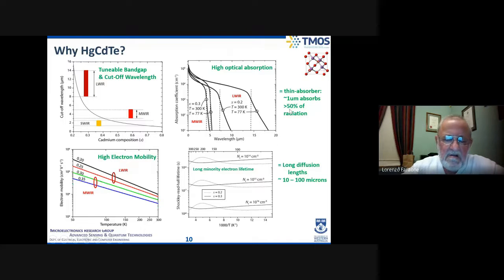So if I have a layer of mercury cadmium telluride that's maybe 4 or 5 microns thick, then I can basically absorb 100% of the radiation. It's all gone, all absorbed in a very thin layer.